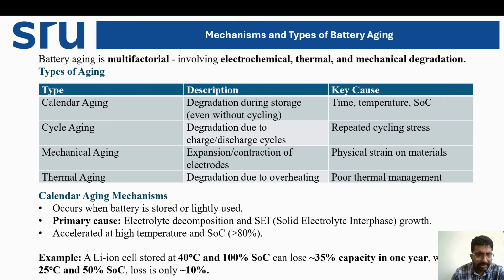So that is also represented here. A lithium ion cell stored at 40 degrees with 100% state of charge can lose up to 35% of its capacity in 1 year, while at 25 degrees and 50% state of charge, the loss is only 10%. So see where is the 35% loss and where is the 10% loss. This can take place because of the difference in temperature and difference in initial state of charge.